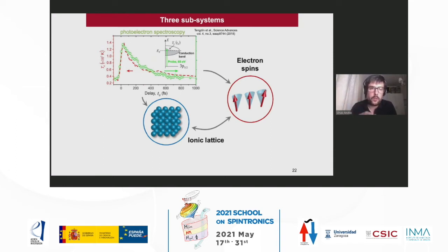What they observe is that after applying a femtosecond laser pulse, the electron temperature increases up to 1,000 or 2,000 Kelvin, depending on the fluence of the laser pulse. So after 200 femtoseconds, the electrons are very hot, and then this electron temperature decays on the order of 1 picosecond or half a picosecond. This is common in magnetic materials.